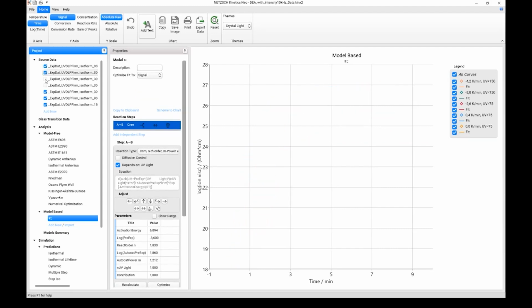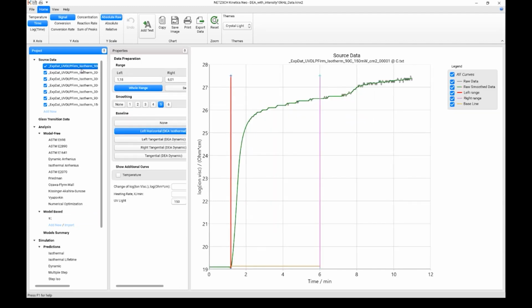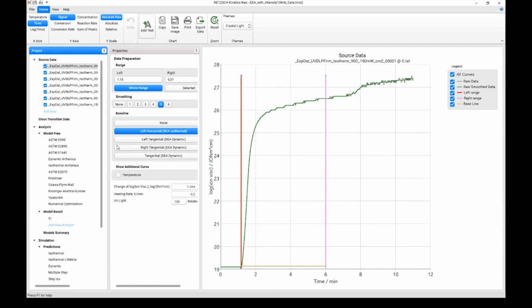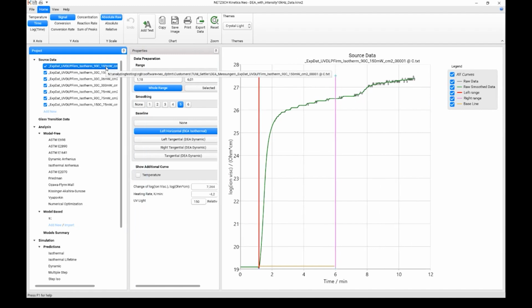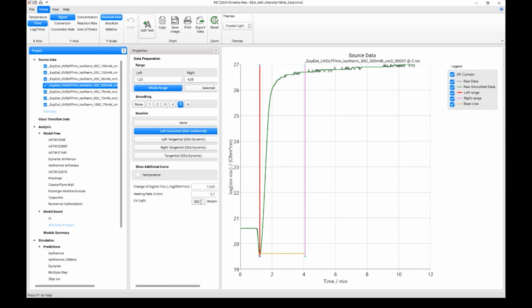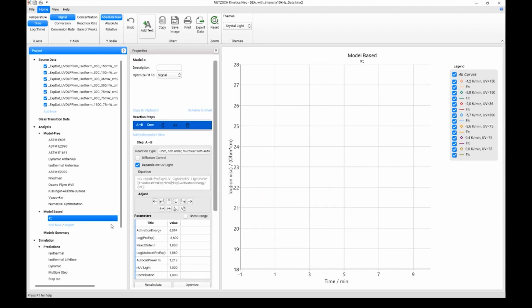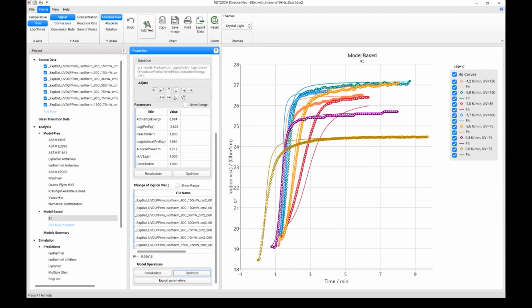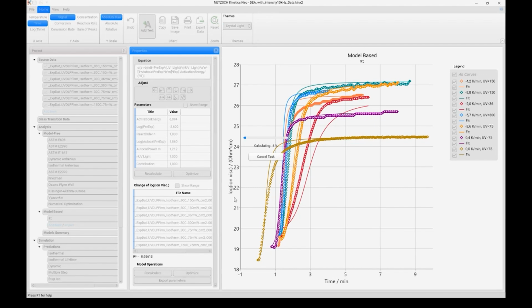Now we will switch on the data which are measured at different temperatures. Let's go here. We have for the first data 150 milliwatt per square centimeter, and we put it here for UV light intensity. For 300 milliwatt per square centimeter, we put here a value 300. And now let's go to our model and make optimization. Now we are waiting until our total model for the curing of our material will be created.